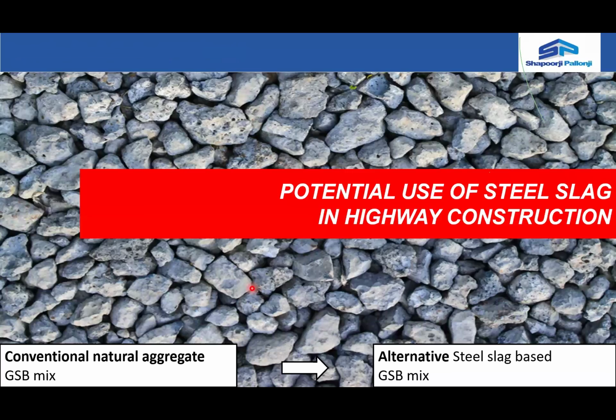Now, the next possible material which we can use is steel slag in highway constructions. Steel slag, the test trials are being done by CRRI in Baroda Halol Road also, if you remember correctly. But the availability of the steel slag is, of course, an issue as far as Indian projects are concerned, because I have faced such difficulties here. But unfortunately, we got the opportunity to use the steel slag in one of the projects in Bangladesh where it is available in plenty. And in that particular project, the GSB mix was chosen to replace the 40 mm aggregates of the GSB mix using the steel slag.